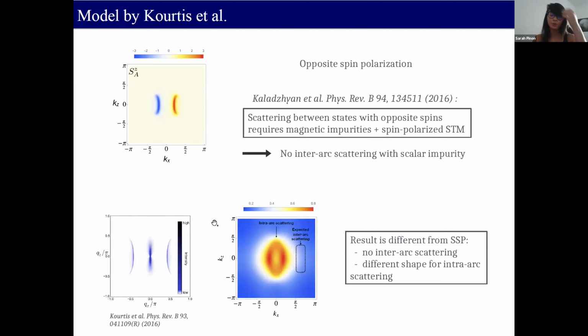These are the results for the QPI. On the left, we have what is obtained by Kourtis et al. using SSP, and this is what we obtained using our method. As you can see, for one, the intra-arc scattering looks different. This is the pattern in the middle of the figure. And also we find no inter-arc scattering, which corresponds to the results we found on the spin polarization of the Fermi arcs. We expected that. But Kourtis et al. still obtained some inter-arc scattering shape, which looks like a wing here.